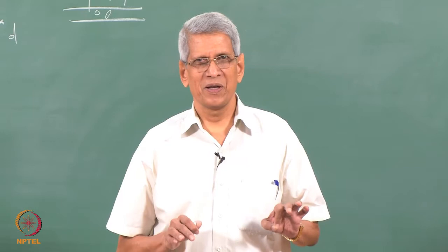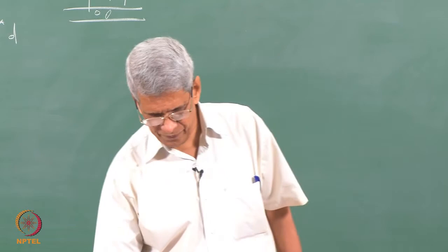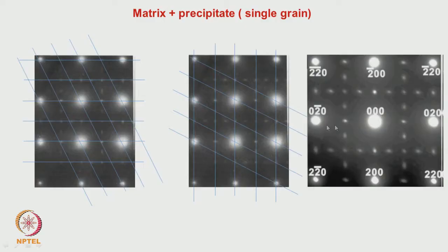So now if we have all the diffraction spots, how they are periodically arranged, that information we have got, correct? Otherwise, if you look at the pattern like this, apart from these central spots, you do not see any periodicity. The first information is to get that, okay. Once this information has been obtained, if you have taken a dark field using these reflections, that helps in identifying whether these spots correspond to one particular second phase particle, or the other choice is that two second phase particles by chance, depending upon their orientation, have spots coming at the same position. So this can also be identified, okay. That we can do only if we take a corresponding image, okay.